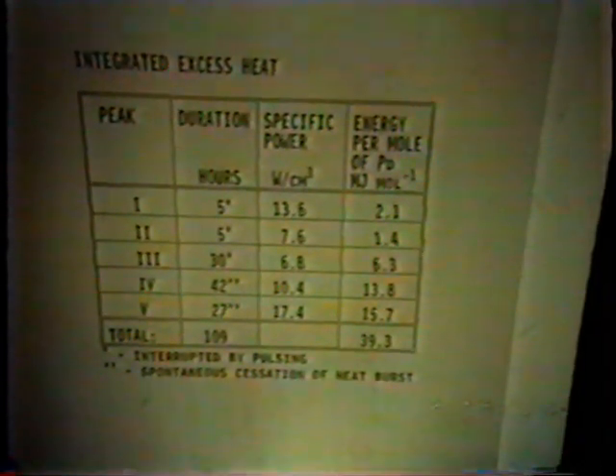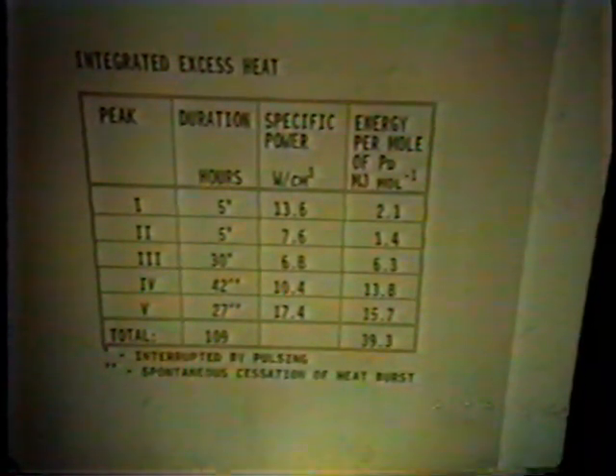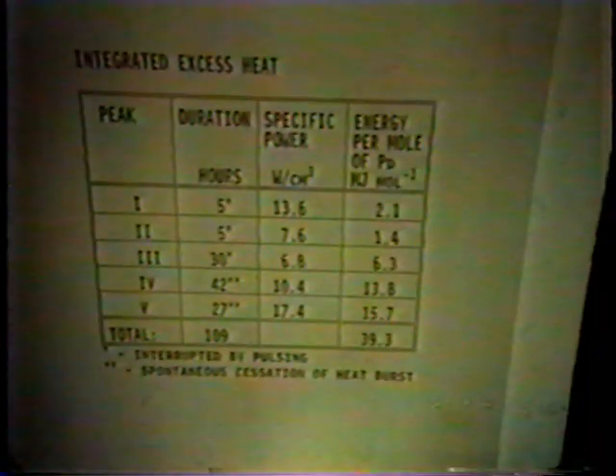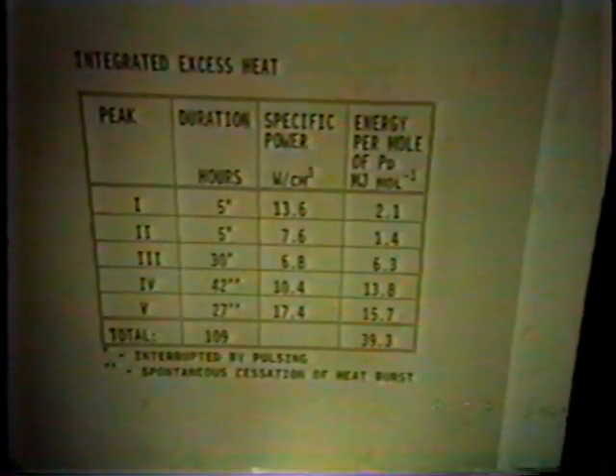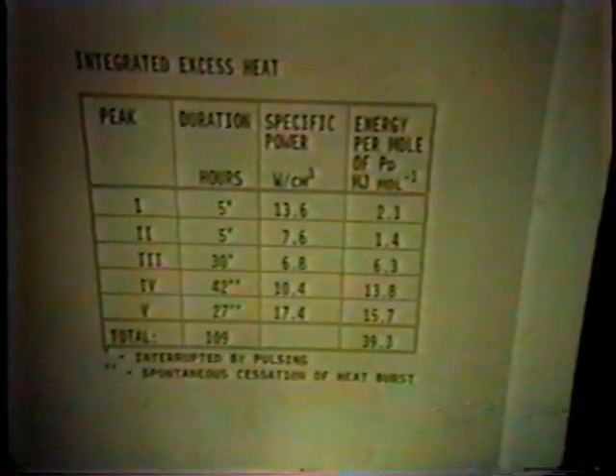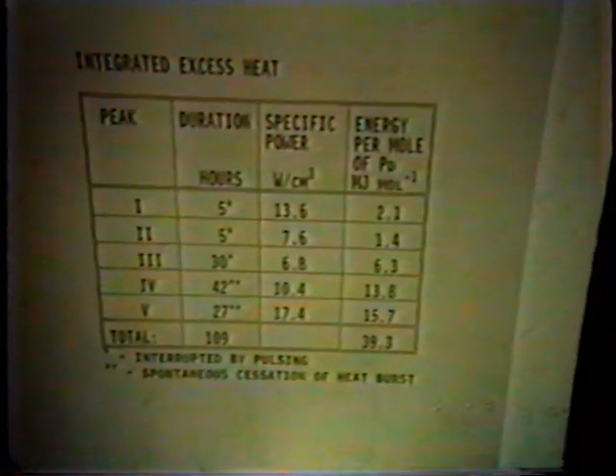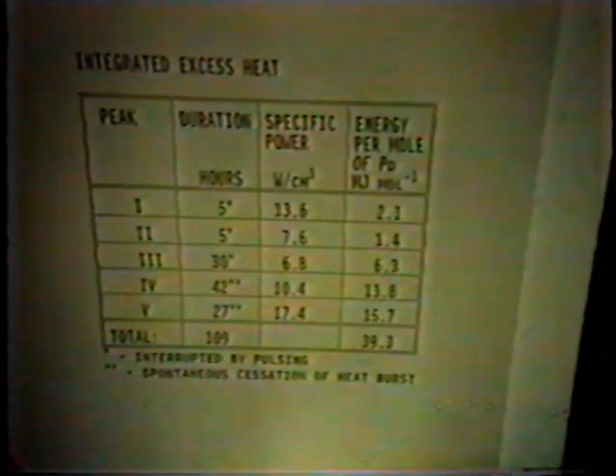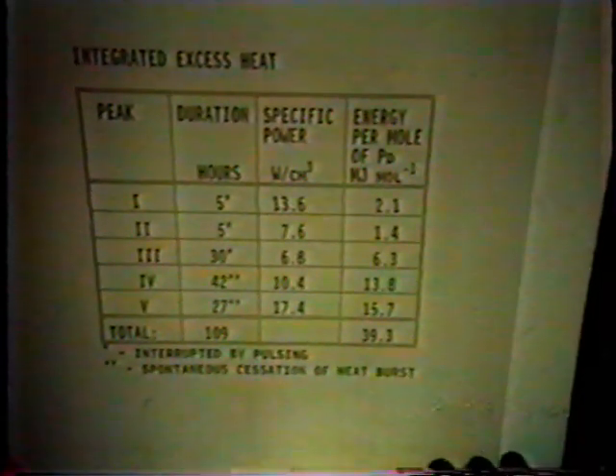And why they stopped? Well, of course, I speculate, but perhaps when you discharge anodically, cleaning up the electrode, you're getting the stuff out. When you put it back again, it's fresh, it's good, and the effect occurs. But of course, there's always a little water. We check this with NMR, but there's always 0.2, 0.3% water there. And the water, the poison, goes in gradually, and perhaps that's the end of the burst when it sets up enough.